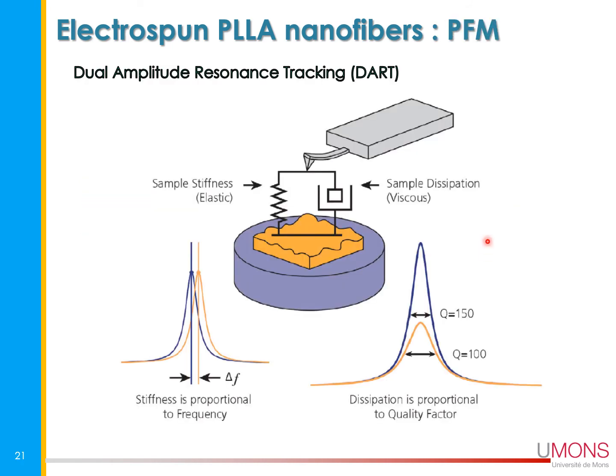Now it's time to move to the piezo force microscopy, and this is what we are using. This is the dual amplitude resonance tracking. I will not enter into the details, but the idea is to be able to measure the resonant frequency, and there is a shift of this resonant frequency, and the stiffness that we want to measure, the mechanical properties, is proportional to the frequency shift, depending on the interaction between the tip and the sample. And the quality factor of this resonance peak will tell you about the dissipation.